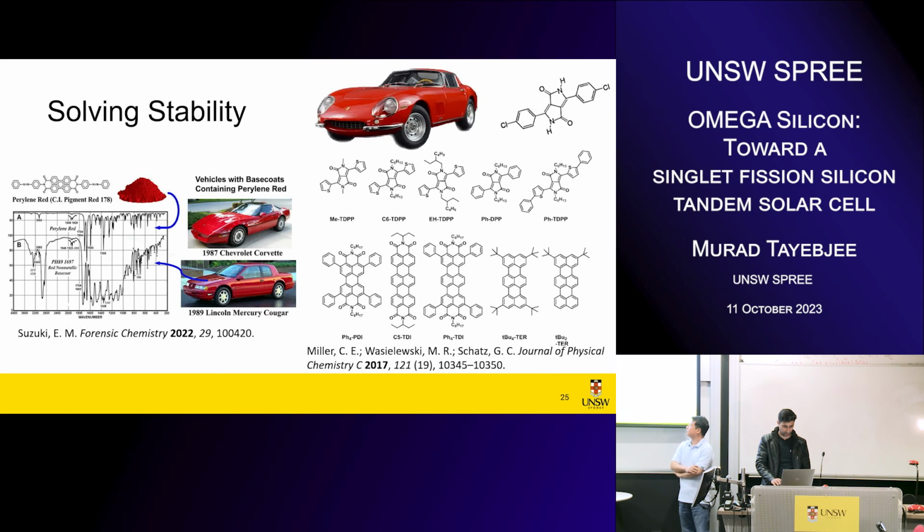Yeah, okay, so excellent. There are two things to consider. One's the central chromophore, where most of the Frenkel exciton sits, and the other is how they pack. First we'd focus on the chromophore by trying to find chromophores that are both stable and have singlet energies about twice the triplet, and of course the triplet has to be higher than silicon's band gap to inject. And if we have that, but they're not doing singlet fission, then you can start playing with the solubilizing group.